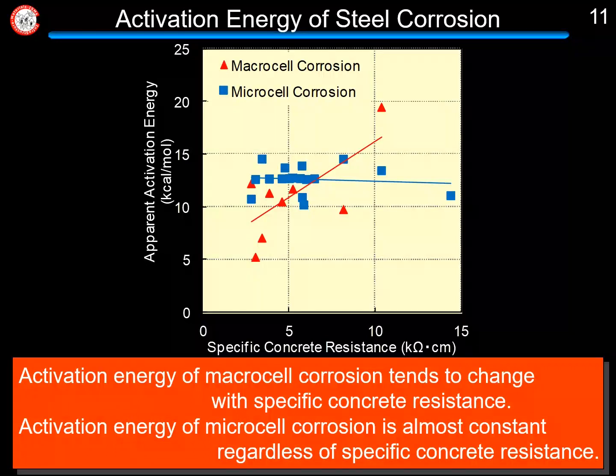This graph shows the relationship between activation energy and concrete resistance obtained by experiment. From this, it can be seen that the Arrhenius activation energy of macrocell corrosion tends to change with increase of specific concrete resistance. On the other hand, activation energy of microcell corrosion is almost constant regardless of specific concrete resistance. So there is a possibility that the macrocell corrosion becomes much higher in warm temperature regions, and it is necessary to pay attention to it.